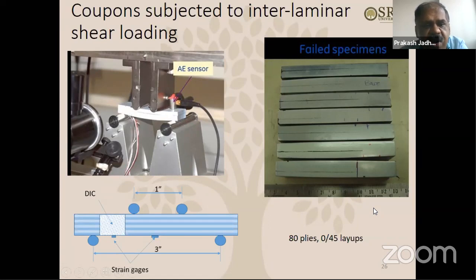So basically, what are we doing here? We are subjecting these ply drop locations to the maximum amount of stress, whether it's a tensile stress, a compressive stress, or interlaminar shear stress. So we are artificially subjecting these ply drops to the maximum amount of stress and then seeing what the effect is, comparing with the specimens without ply drops.